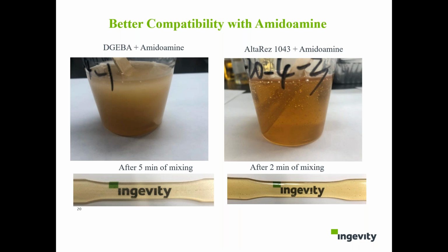This is AltaRez epoxy cured with amidoamines. You can see AltaRez epoxy is much more compatible with amidoamines compared to bisphenol epoxy, the EPON 828. On the left-hand side, after 5 minutes, AltaRez epoxy with amidoamine turned very clear. The right-hand side picture, after cure, is a very transparent, clear casting. The left-hand side represents the control, the bisphenol epoxy with amidoamine. After 5 minutes, it is still hazy and not transparent. And after cure, again, it is not totally transparent and also looks opaque.